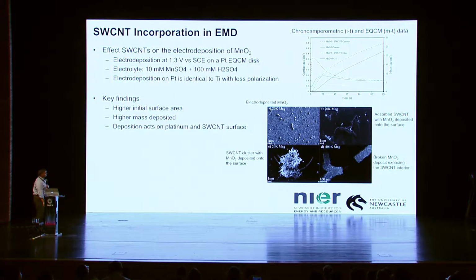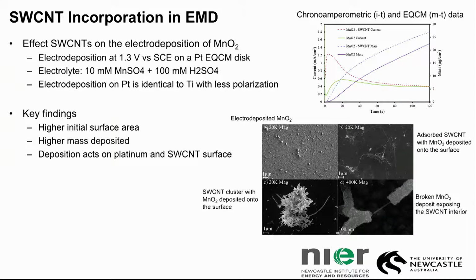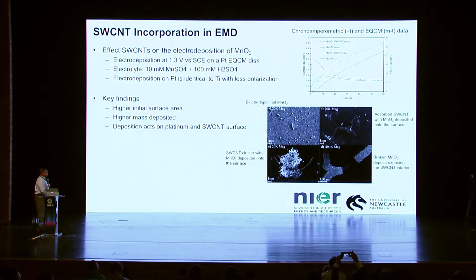Okay. So we've done a lot of work exploring the inclusion of carbon nanotubes into the manganese dioxide structure, basically an in situ inclusion of them into the structure. And one thing that I really like is this little image down on the bottom right-hand corner here. This is manganese dioxide that's been found embedded around a carbon nanotube in that particular system. So it's essentially just a piece of broken manganese dioxide with a carbon nanotube that was embedded in the centre of it. So we've found a lot of interesting outcomes from this in this particular case.